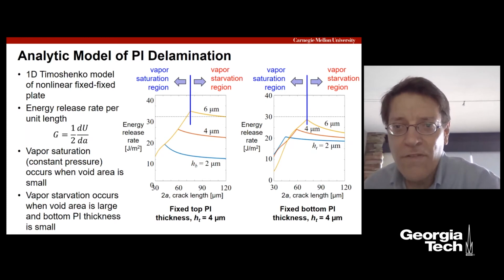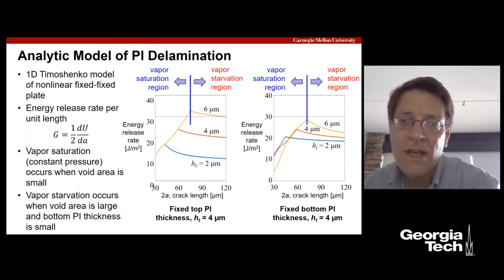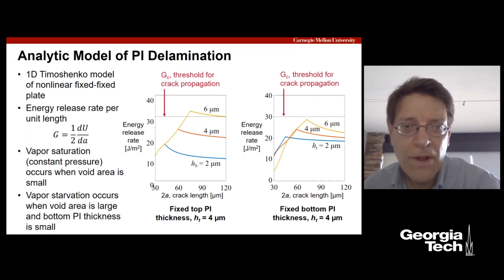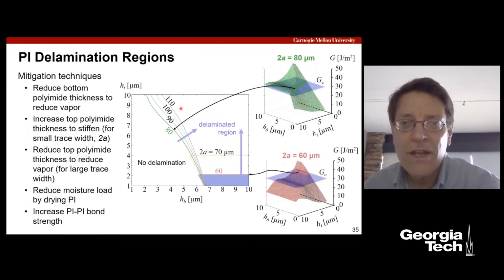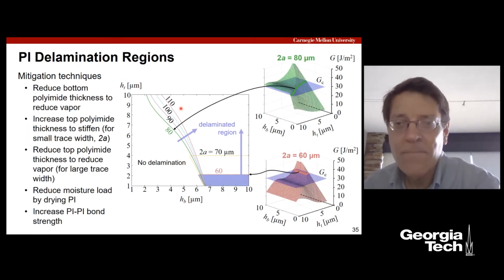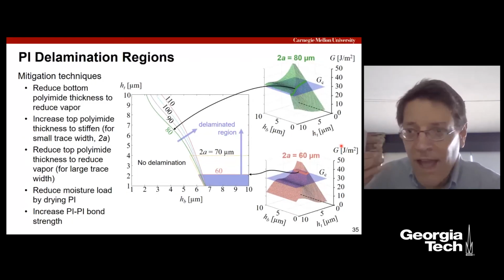The other thing about the vapor starvation region, as it goes down and the crack length gets larger and larger, is that the energy release rate is not dependent on the top thickness. It's only dependent on the bottom thickness, as you can see in the right plot. And so this gives us a lot of good insight into what's going on. You can see this is where the crack propagation is, and we can predict where we're going to delaminate. I don't have time to walk through all this, but what we did is plot 3D plots of the energy release rate versus the top and the bottom polyimide thickness for various crack widths, and a crack width in our case is how wide we're making the trace.